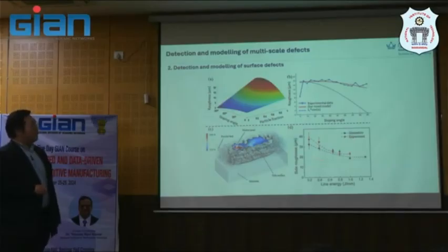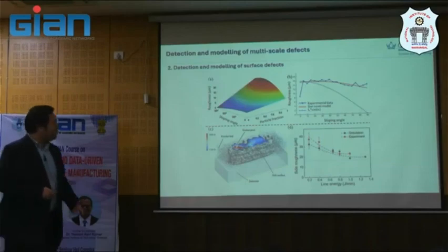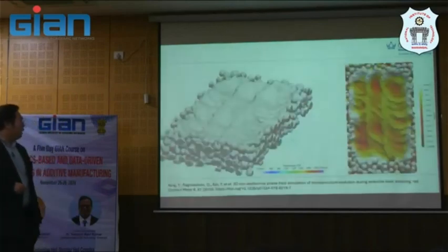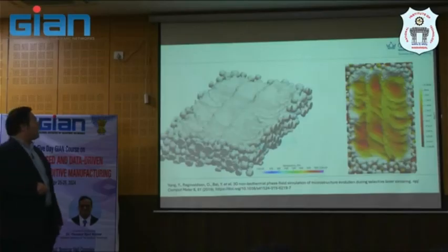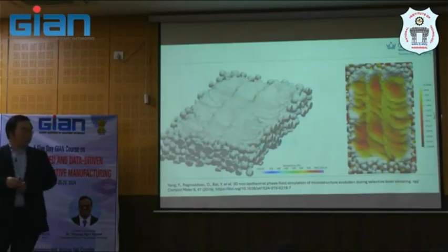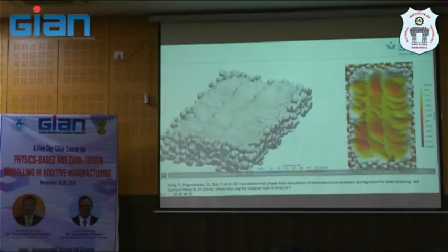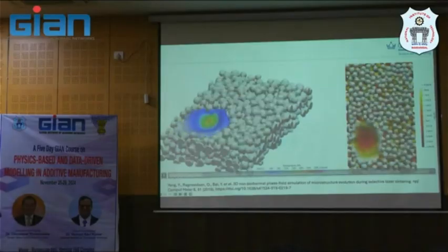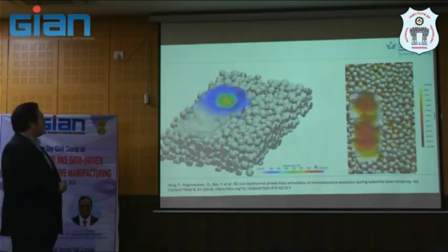But I think it's quite good agreement with experimentally measured roughness here, with very line energy density. But anyway, that means things need to be improved a little bit more. Another example is related to this evolution, but this is not really intended to be melting, this is just sintering the part.